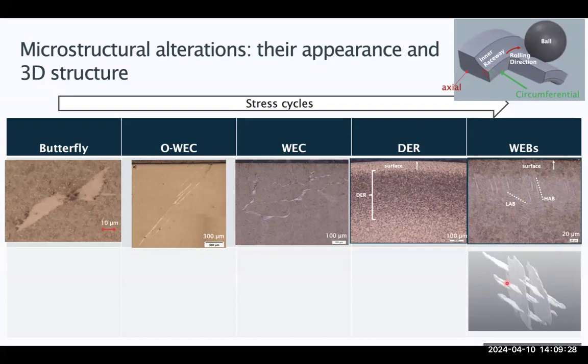These are the low angle bands at 30 degrees. These are the high angle bands, at 80 degrees. They are not just strips, they are actual plates going into the thickness of the ring. So it looks like networked bands in the material. This is, again, the first time ever that people have shown the 3D structure of the white-etching bands.